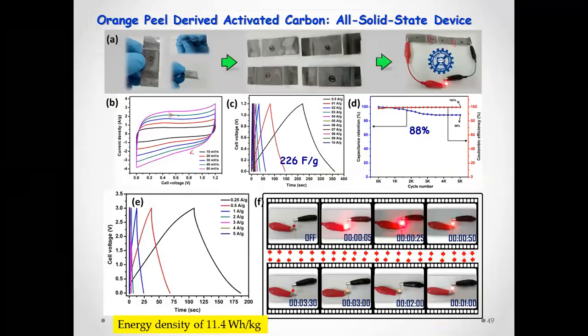So here I will show you a very small thin device. Here you could see this image. There are 3 or 4 devices connected. Here you could see this is a small device. So this is a carbon plate. On one side of the plate we have coated this carbon. The other side also we have coated, and in between we kept some solid gel electrolyte, PVA sulfuric acid or PVA KOH gel electrolyte, that could be clipped. Then you can end up with a device.